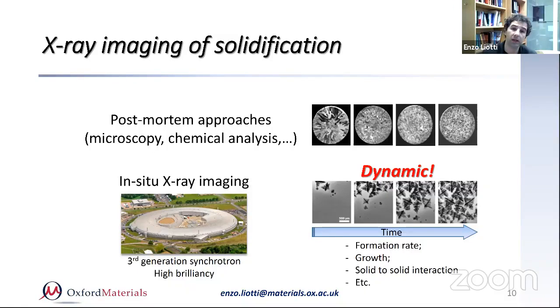Traditionally, metallurgy has been studied by post-mortem approaches. So the typical case is what I just said: you take a sample, you cross-section it, and you look at it with an optical microscope or an SEM, and you see the microstructure. However, it doesn't actually tell you the entire story, because the microstructures you attain in dynamic processes are often the results of the process itself. So looking only at the final stage might not tell you the entire story.